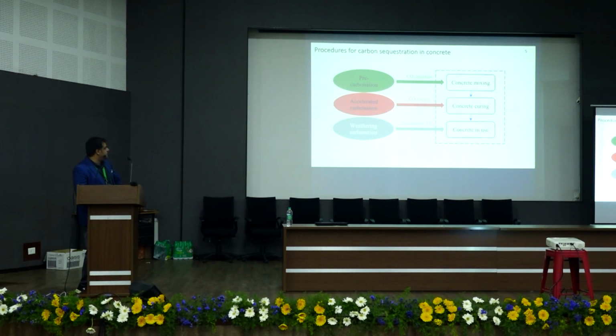The second one is during the curing of concrete. So that is called the accelerated carbonation, where you cure your concrete under a CO2-rich environment at a particular concentration, and you can mimic how much CO2 concentration is there in the flue gas, and you can dose it accordingly. And finally, the natural carbonation, which is a very, very slow process, and it takes about 20, 25 years to carbonate even the top few mm of concrete.